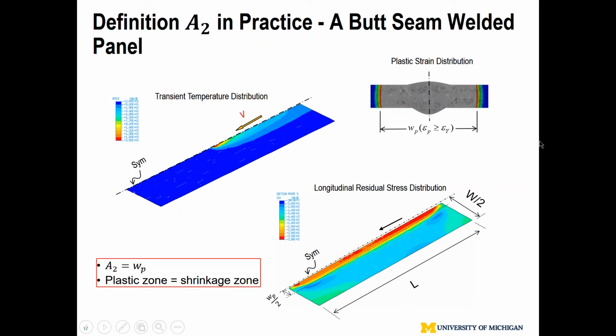That's why in the NASA friction stir welded ring, the residual stress is always above yield along the welding direction, which triggered buckling. The residual stress within that area will be tensile, and on the side, they balance it by force equilibrium, where the total area has to be equal to 0, total moment equals 0. So the message on this chart is the 2 times delta Ty criterion is pretty easy to reach when you talk about typical structural assembly.